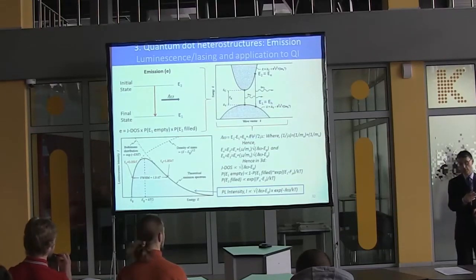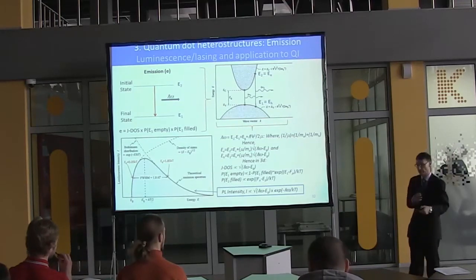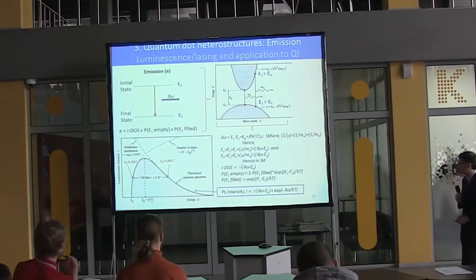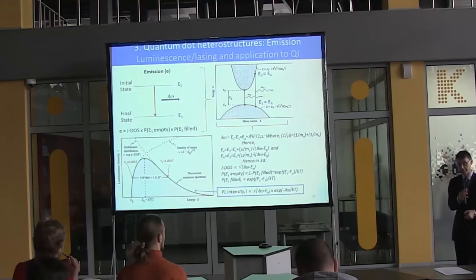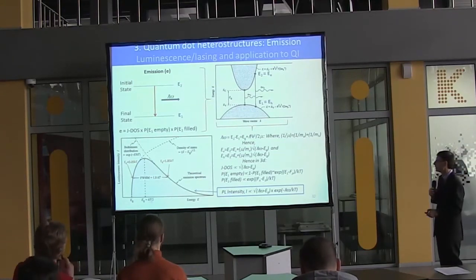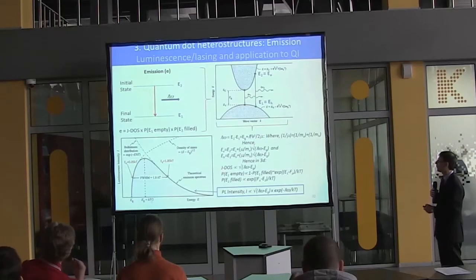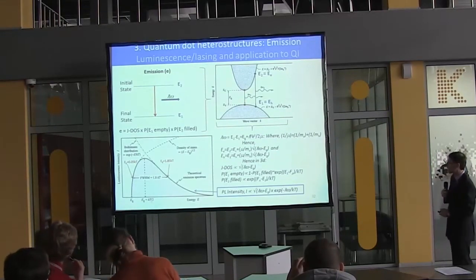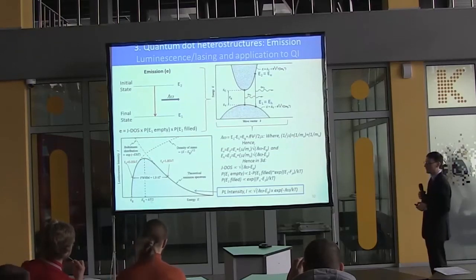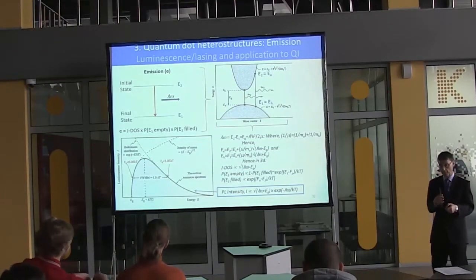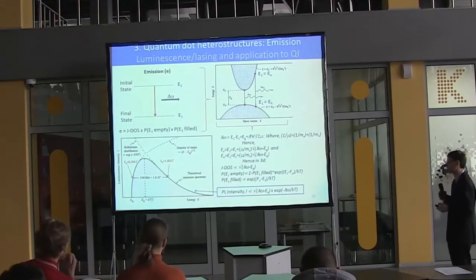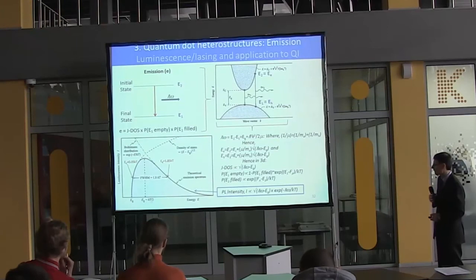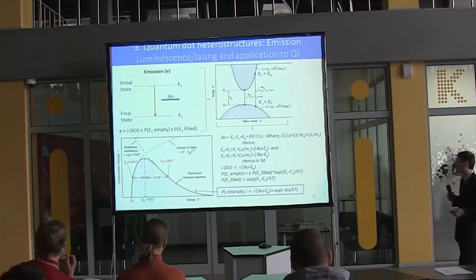So if I said, what's the spectrum of emitted light from a laser in terms of the population argument, which is this, I'd expect to see something which peaks not at the band gap, which is what I've told you all along, which is why I kind of did this, not at the difference between these two here, or not at the difference between here and here, but slightly higher, because you've sampled the population, or weighted the population, by where the carriers actually are, where the available states are, and so forth. So that gives you something which, roughly speaking, has a narrowish half width, goes up to about 1.85 kT above, or 1.8 kT wide, if you like.